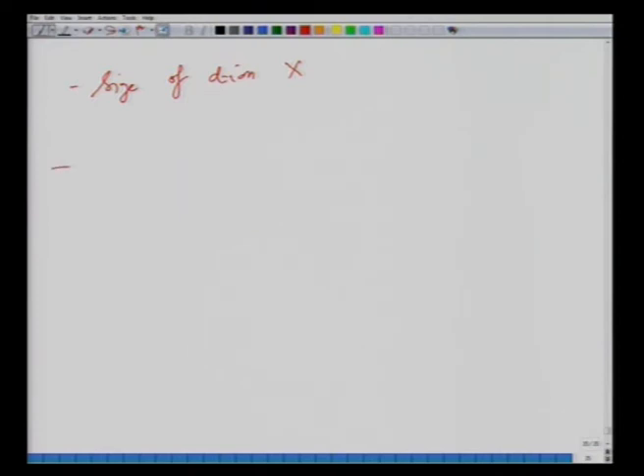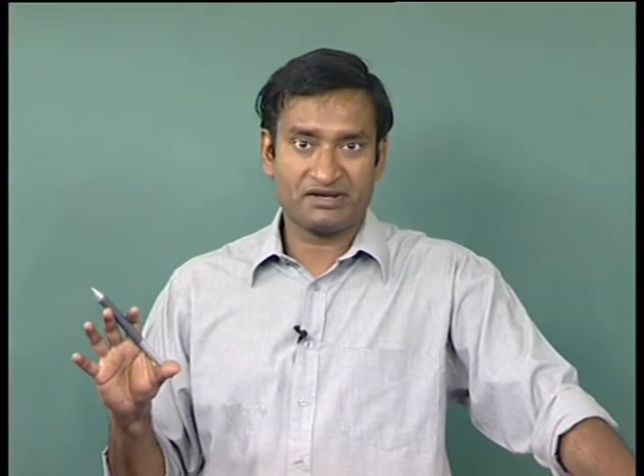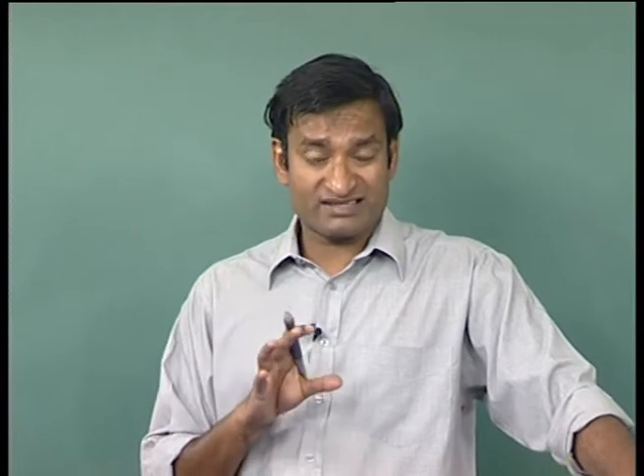And then you had structural distortion. This is interesting because in ferroelectrics, when you cool across the Curie temperature, you have a distortion from a high symmetry phase to a low symmetry phase, and this low symmetry phase does not have a center of symmetry. As a result, your material is ferroelectric. So the center of symmetry has to be broken. In the case of a ferromagnetic material, when you are in the ferromagnetic state, you have a Jahn-Teller distortion. This Jahn-Teller distortion requires that the center of symmetry is maintained. So this is the paradoxical or conflicting requirement of structural distortion in both of these materials.